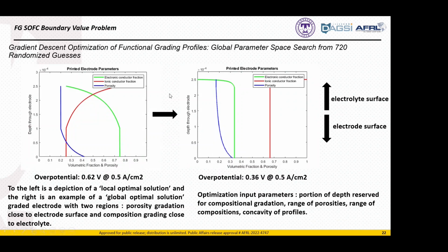So first we did some single parameter optimization where we just tried to minimize the overpotential. And here's just briefly a result from that on the right-hand side. So starting at an initial guess such as this on the left-hand side, we come to a solution like this on the right-hand side using gradient descent optimization.